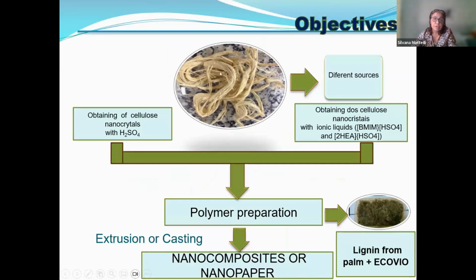First, we use different sources of cellulose. We obtained the nanocrystals of cellulose with sulfuric acid and with the ionic liquids. We prepared the polymer by mixing lignin and Ecovio, that is PBAT with PLA, for a polymer preparation to extrude it better. And also for casting, we prepared the nanopaper. So we have nanocomposite and nanopaper materials.